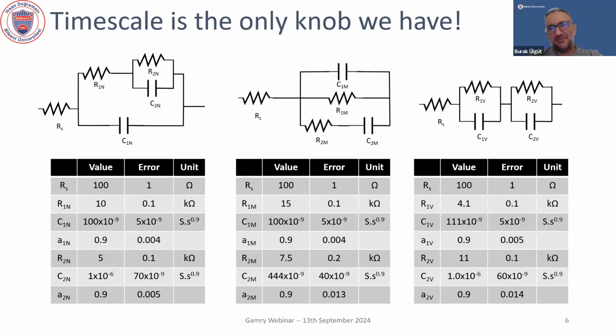Now, the errors I'm showing are just the fits that I've done after I've done the simulation with one of them. But this is a problem. There is no way impedance spectroscopy can tell you whether your system behaves like the nested model, like the defective corrosion protective coatings do, or the void model on the very far right, like most fuel cells do. So you have to do your homework in addition to taking impedance spectroscopy in order to identify which model to use, and further, whether the R1C1 or R2C2 belongs to the anode or the cathode or vice versa, because the impedance spectrum will not tell you which is which. It will only tell you that there's a process that's fast, there's another process that's slow, and it'll tell you the parameters of the two, provided you know which model to use.